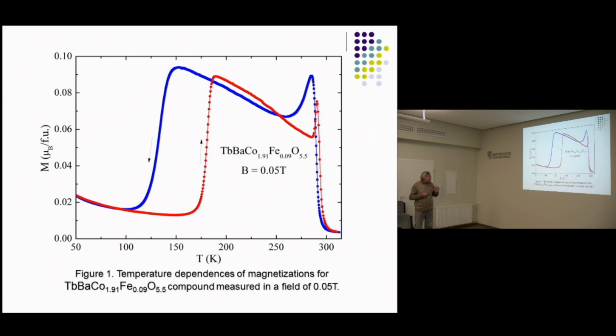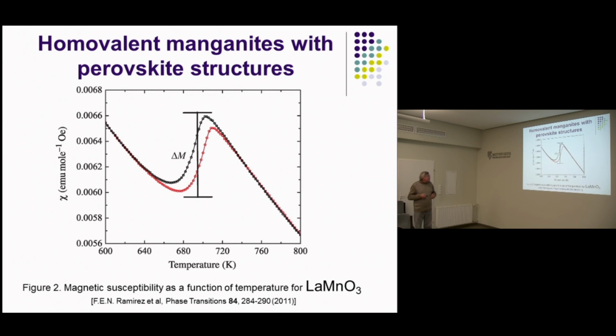This slide is a compilation of this history. This compound, a homovalent manganite with perovskite structure, also exhibits a transition from orbital ordered to disordered orbital structure. This phase transition is associated with a jump of magnetic susceptibility, but in the disordered state, this compound is ferromagnetic.